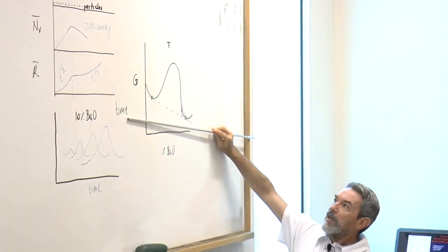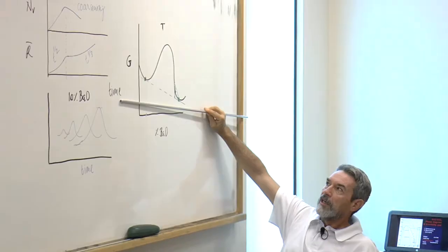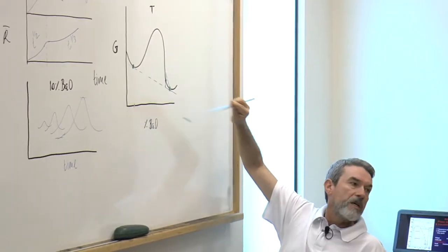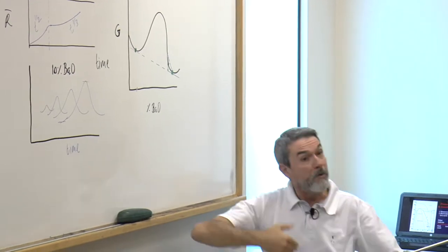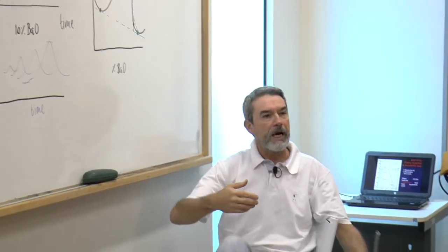Of course, there is an even lower free energy here, which is the free energy of the crystalline state. So the system will continue to evolve after liquid phase separation towards crystallization. It's not yet in the lowest free energy state.